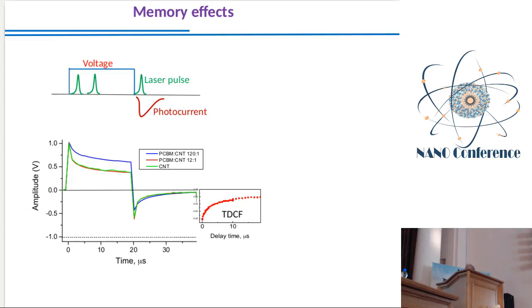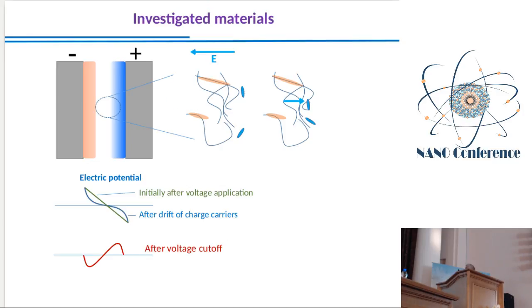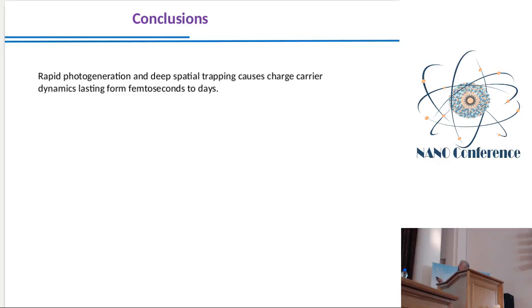These charge carriers are trapped in so-called spatial traps. We generate an electron, and it goes to some place where, when we reduce the electric field, it cannot go back, and we have a very, very long memory effect. My conclusion is that rapid photogeneration and deep spatial trapping cause charge carrier dynamics lasting from femtoseconds even to days.